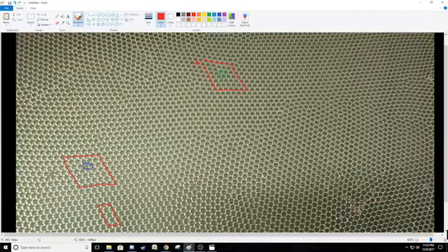You almost draw an arrow saying, look, somehow this part of the box has shifted one down in this direction. And that is our Burgers vector. It shows how much this dislocation has affected the crystal structure in this area. So that's how you draw a Burgers vector and what it means. It gives us a way to quantify the dislocation and its effect on the crystal structure.